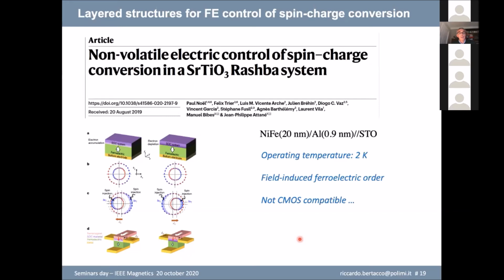a ferroelectric material. And what they found is that even though at very low temperature, you can really change the spin to charge conversion when you inject now a spin current and you observe now a charge current. You can change the spin to charge conversion by changing the ferroelectric state, as it is shown here. Okay, that's a very beautiful paper, a very nice demonstration of the concept. Obviously, there are some limitations.